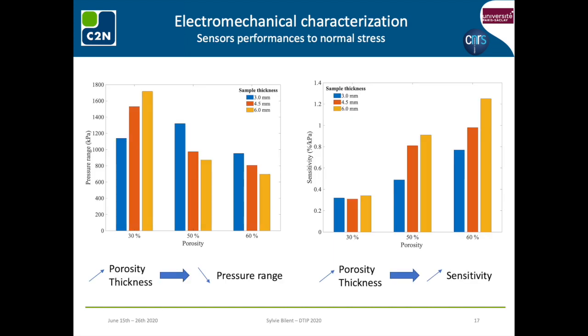As a summary, we gather on these two histograms the evolutions of the sensor pressure range on the left-hand side and the sensitivity of the sensors on my right-hand side according to the porosity and thickness of the used scaffold PDMS layers. For the fabricated sample, the observed general tendency is that the pressure range decreases as porosity increases and the sensitivity increases as porosity increases.